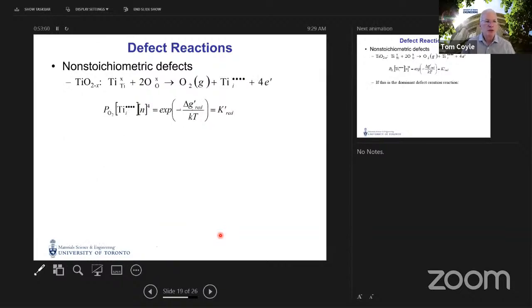There are other defect creation reactions that we can hypothesize that would explain how TiO2 could lose oxygen. So for example, another possibility is that oxygen is lost from the lattice to the atmosphere, and to maintain charge balance, instead of creating oxygen vacancies, perhaps we create titanium interstitials with a relative +4 charge, and that we balance charge by creating 4 electrons in the conduction band.